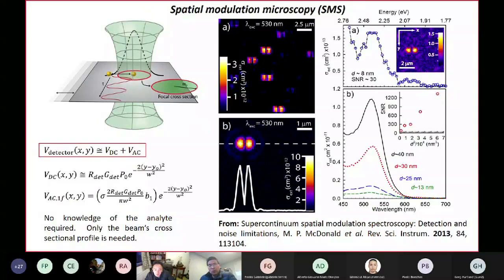If you look at the absorption spectra or extinction spectra, and let's assume that the gold particle is representative of some object or general object of interest, you'll note that the transitions are fairly broad, many nanometers wide. Consequently, electronic transitions in the visible part of the spectrum are usually fairly broad, and they don't have chemical specificity. For example, if folks really want to know the chemical identity of something, unless you exactly know you're looking at a gold particle, I could confuse this for something else in principle.